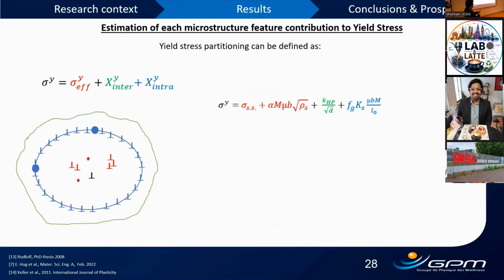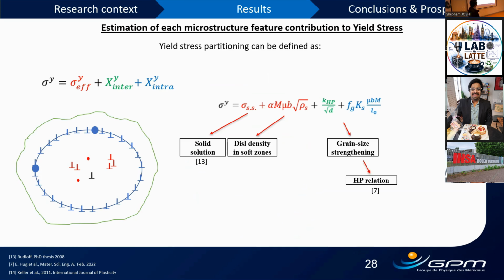If we look at this slide, we can see the model that we considered. The effective stress, we believe, is connected to solid solution and dislocation density in soft zones. The intergranular back stress portion is connected to grain size strengthening, which is the Hall-Petch equation connection. And finally, the intragranular back stress is connected to the initial dendritic cell size that we computed in the initial microstructural stage.